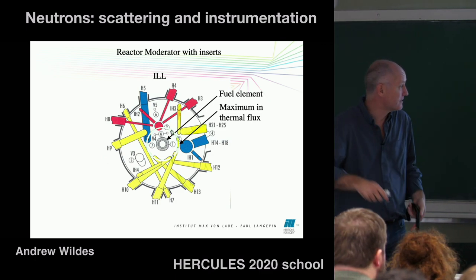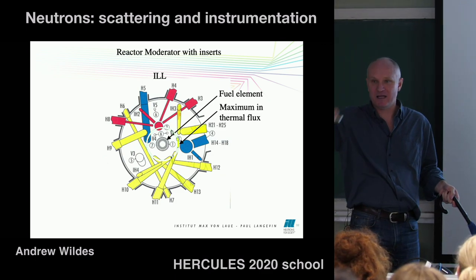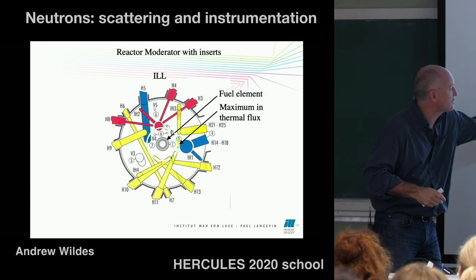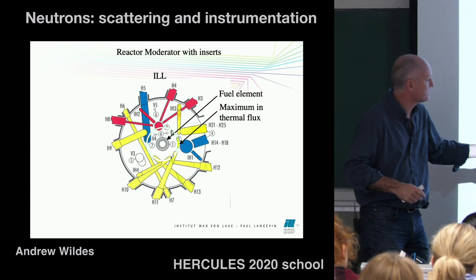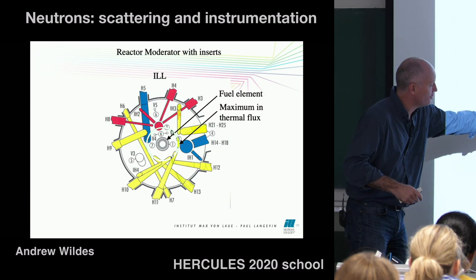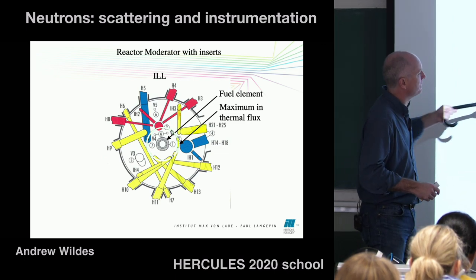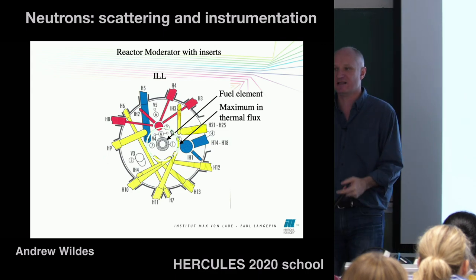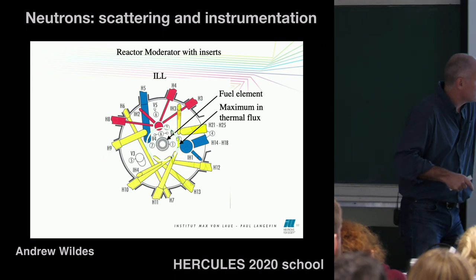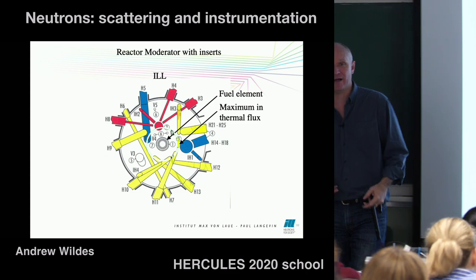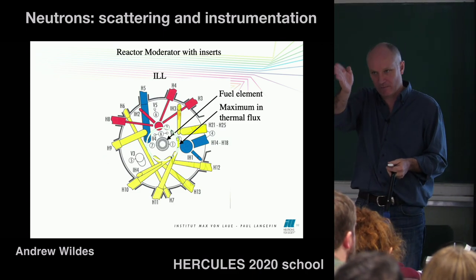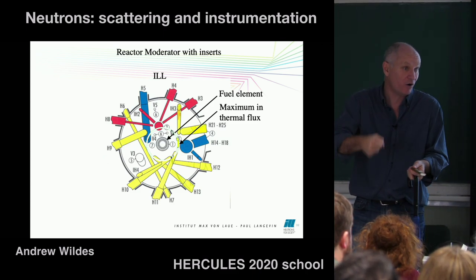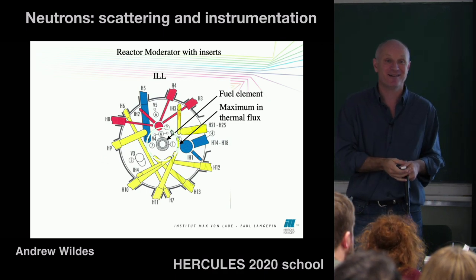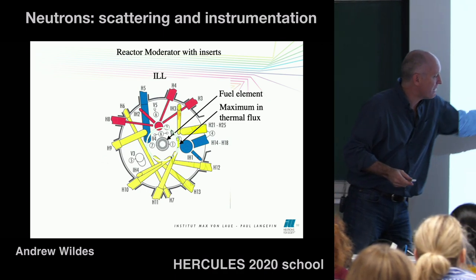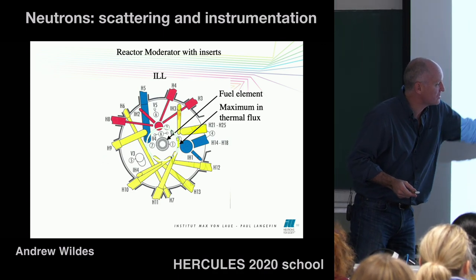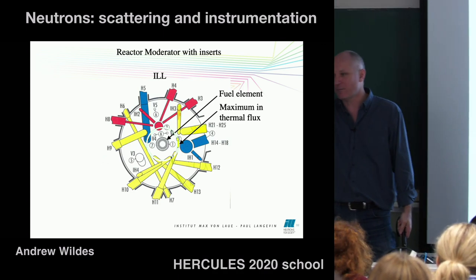This whole lot is sitting inside heavy water moderator, and it turns out you get a maximum in the flux of your 300 Kelvin neutrons at a certain radius. And what you can see here is all these beam tubes. This is where the neutrons come out. They're all pointing more or less tangential. All these yellow ones are pointing more or less tangential to that radius there, to a circle of that radius. So the idea is that the neutrons have got your maximum in that flux there. You literally drill a hole in the side of the reactor and hope that some come out. That's the way that it works. And you're going to get the maximum number of neutrons coming out along this direction if you're pointing it where the maximum of the flux is.